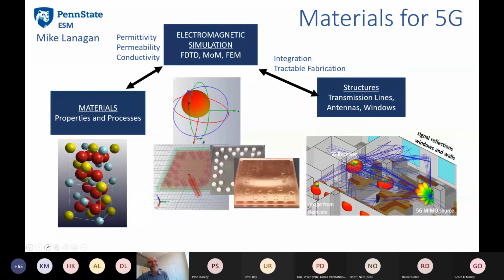And once you go for the resonant technique, you really then have fixed frequencies. I've seen some really nice work at NIST, for example, where they've taken a cavity and looked at a variety of modes. Within that one cavity, like I showed just one data point for that split cavity, they've taken the modes and were probably getting 20 data points through a frequency range. Still discrete, but it still gives you a resonant technique for high Q and somewhat of a broadband as well. That's always a trade-off. It always will be, because there are fundamental differences between a transmission reflection measurement and a resonant measurement in terms of bands. Yeah, that's a really good question.